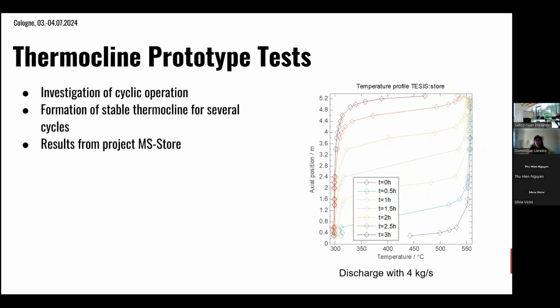So these are some results from the first experiments we did with the initial thermocouple tree. As you can see, there were a lot of thermocouples that apparently failed, but we were still able to measure the thermocline profile inside the tank. And you can see there's a very good stratification achievable. This is more than 5 meters in height, and the thermocline thickness itself is way below 1 meter. So the results we achieved were quite satisfying, and we will also maintain that for several cycles.